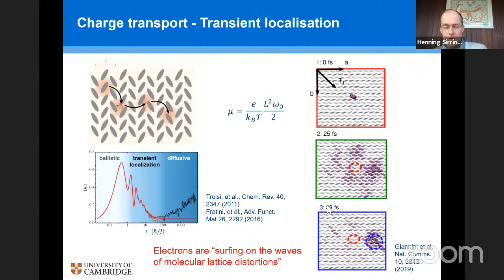You can see a beautiful visualization of this calculation here on the right-hand side, where you have, I think, a pentacene lattice again, where at time t equals 0 you localize the carrier at this particular point in the lattice. This colored spot indicates the molecular wave function highly localized at that point. And then you can basically follow it as a function of time. You can see here that after 25 femtoseconds, the wave function is much more delocalized over a cluster of maybe hundreds or almost 100 molecules in this case.